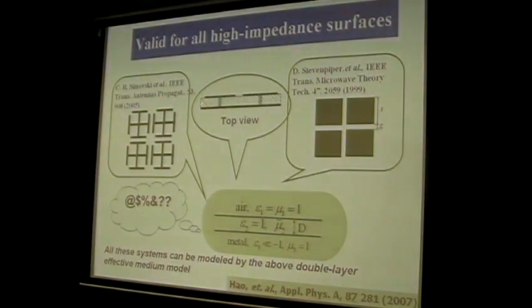Indeed, we found that our model can work for all kinds of these complex structures. You can replace the fractal structure by this cross structure, and you can also replace it with a square structure. No matter how complex these structures are, for this kind of three-layer system, you can always characterize the complex structure as a double-layer effective medium model, which is composed of anisotropic magnetic material put on the perfect electric conductor.